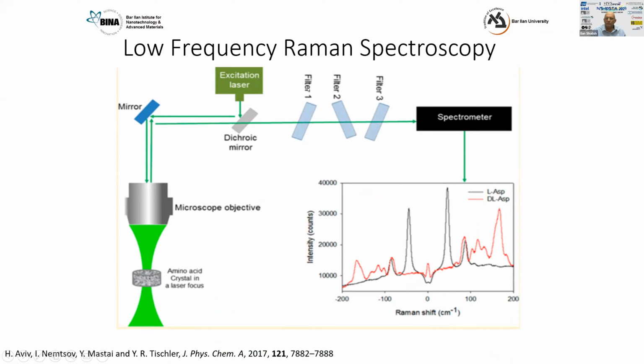And then the magic sauce is these special filters. In this case, it's a series of 3 filters. These are called volume holographic filters. And what's special about these Raman filters is they have a very, very narrow stop band, about 10 wave numbers. So if you look here at the low frequency Raman scattering, you can see there's only a small region, about plus or minus 10 to 15 wave numbers, that's actually where the laser is blocked.